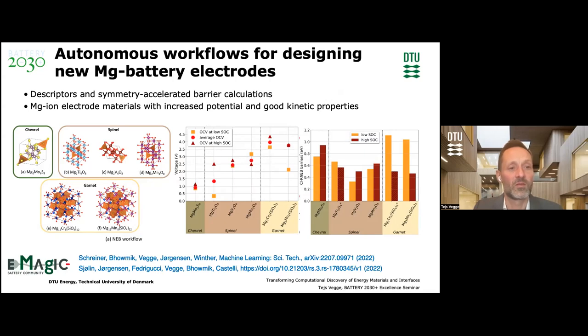So both Chevrel, Spinel, and Garnet, where through this relatively simple workflow, you could see the potential at low and high state of charge, but you could also see, as indicated here on the right, the potential for fast charging of that specific electrode, for instance, some of the spinels here at low and high state of charge. So this is a way that you can map out all the potential structures and get information about the thermodynamics, as well as the kinetic properties.